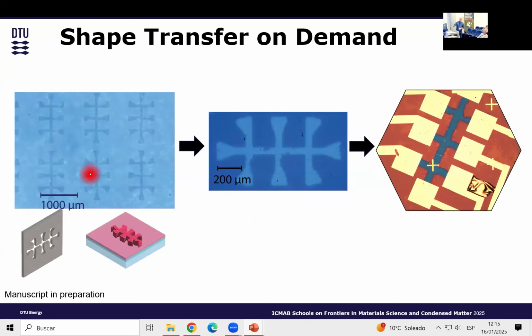So this is a shape of what looks like a Hall bar. This is because that was the mask shape. So it's just a replica of the mask. We could take one of these Hall bars and put it on a silicon. So this is on a silicon. We put leads onto it, and then measure whatever we want to measure. Now, some of you with good eyes could see that there is a defect here, and there are defects here, and defects all over, basically.